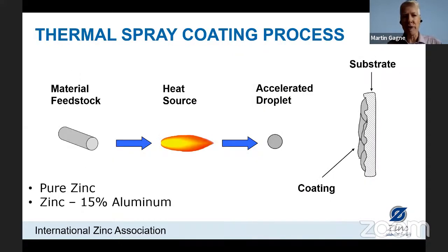So the process itself is quite simple. We have a material feedstock. We apply a heat source to melt that zinc. Then we accelerate the drop against the surface and we build up a coating. Now for zinc, we can have pure zinc. There's also a zinc 15% aluminum alloy wire. Both of these are very commonly available. There are some other chemistries, but these two are available, perform well, and are most commonly used.